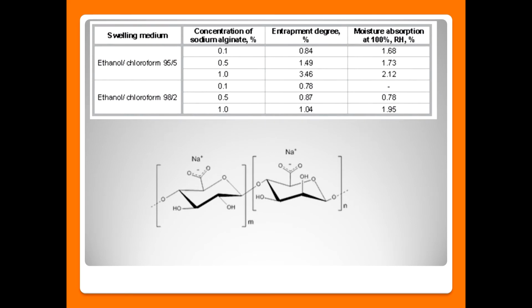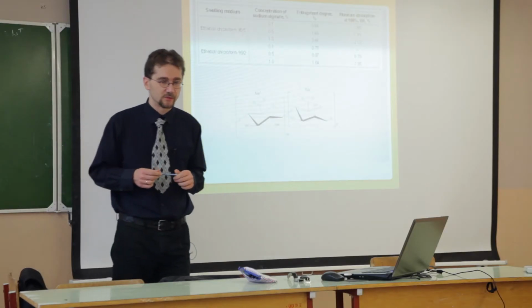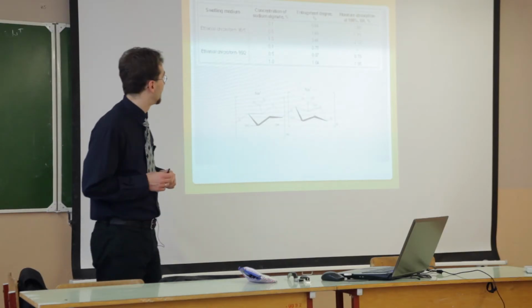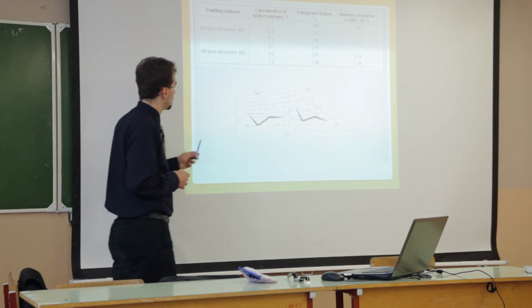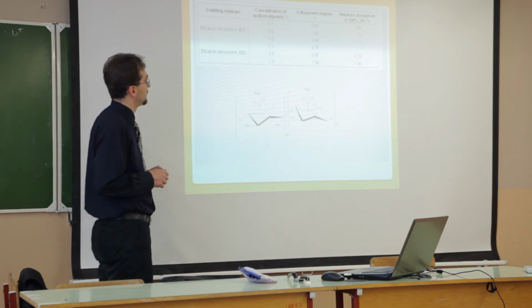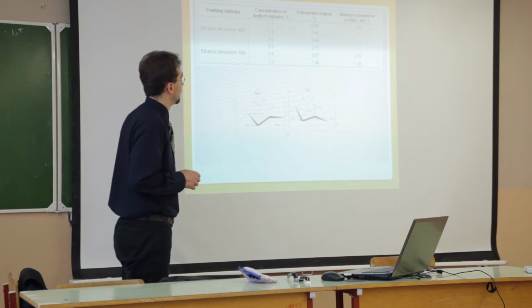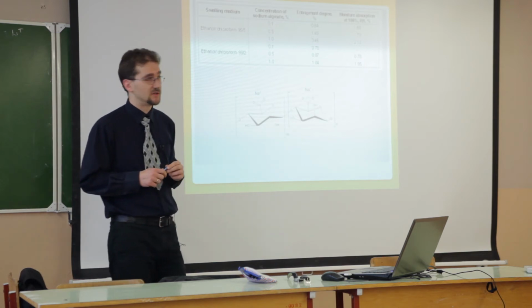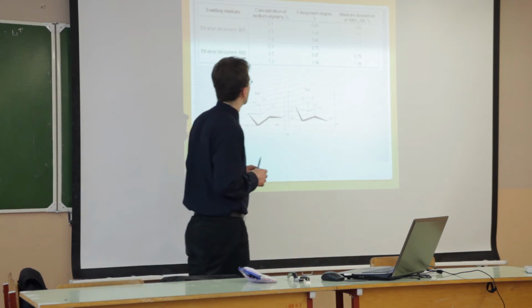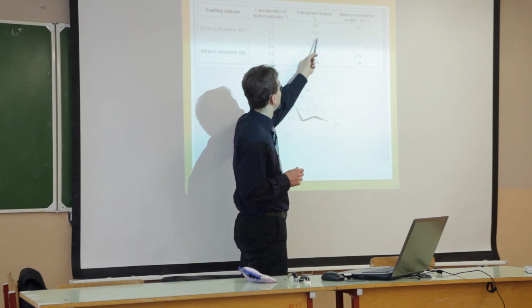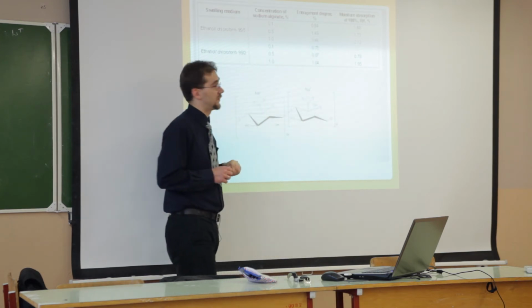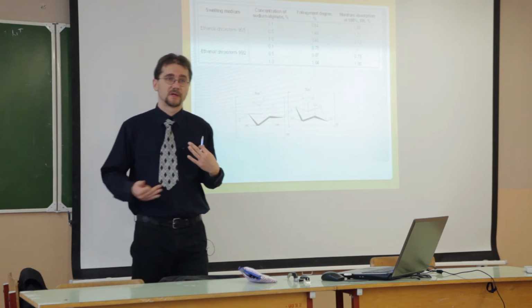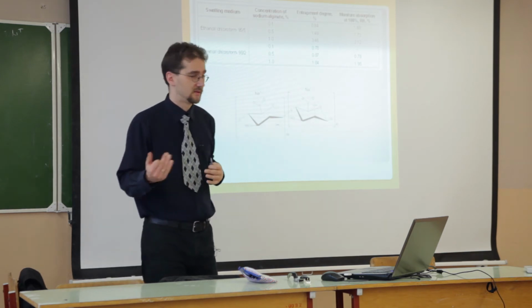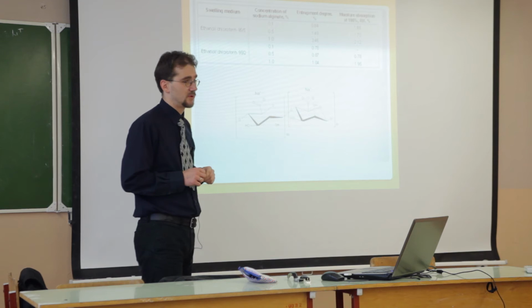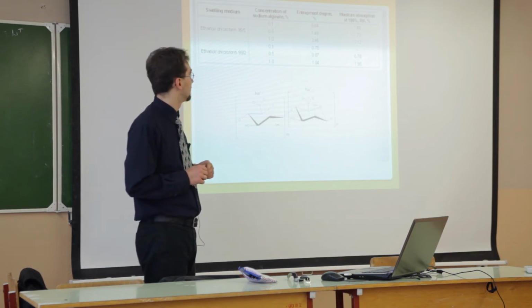We also tried entrapping different polymers on the surface, such as sodium alginate, as you see here, again changing conditions. Finally, we obtained an entrapment degree in percent, which can be controlled by weight, and it was more than 3%.